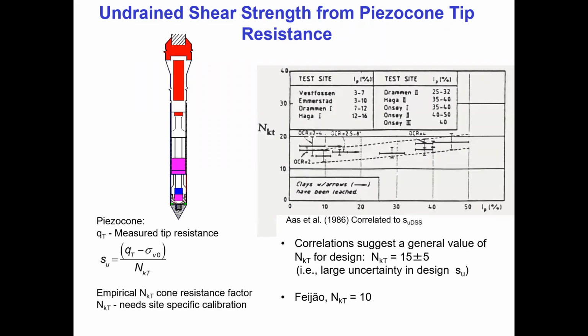How does this work out? Well, if you look at global data sets, NK varies. NK is not a universal constant because the more brittle the material is, and the stiffness of it pre-peak, all affects the tip resistance. So there's not a universal value of NK. You would generally do site-specific correlations.